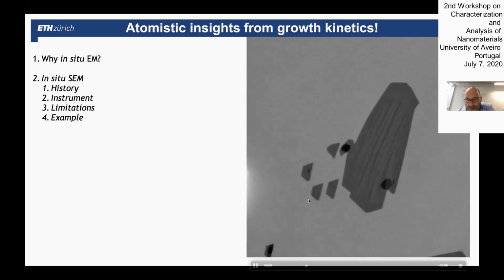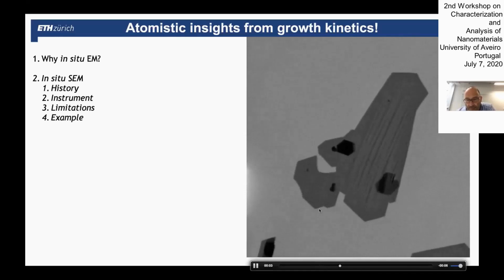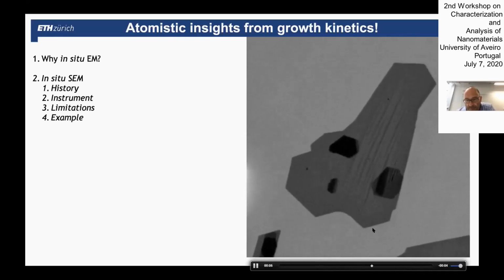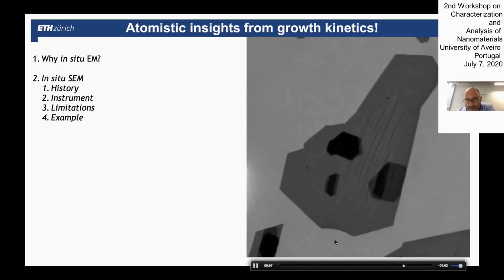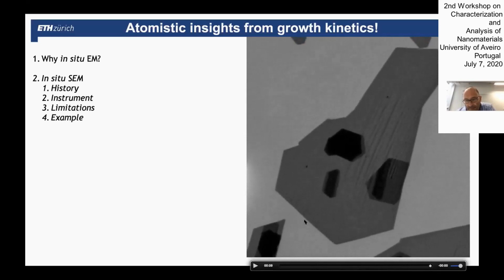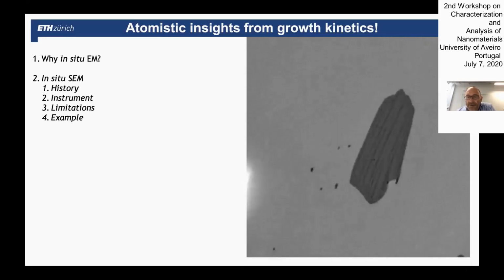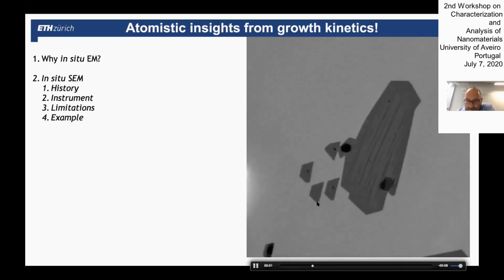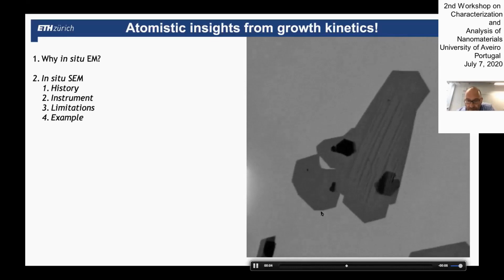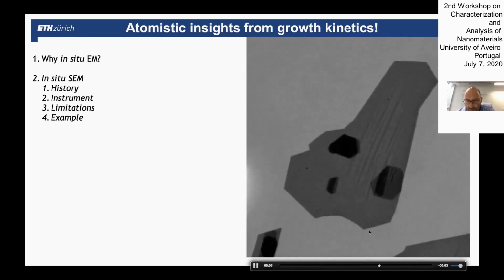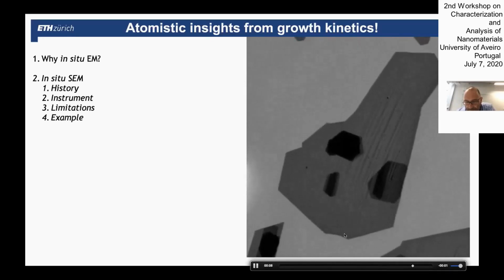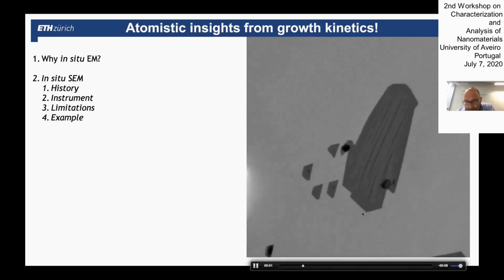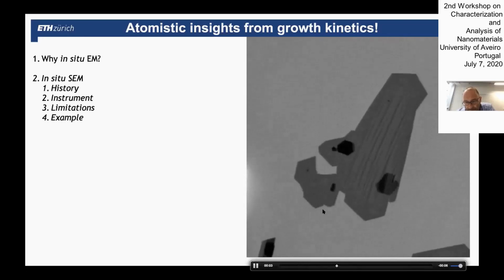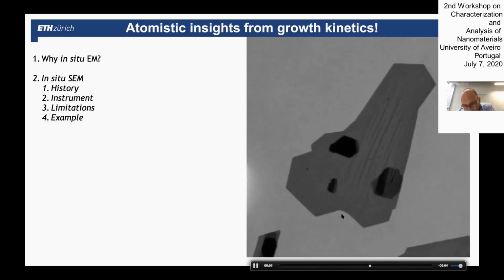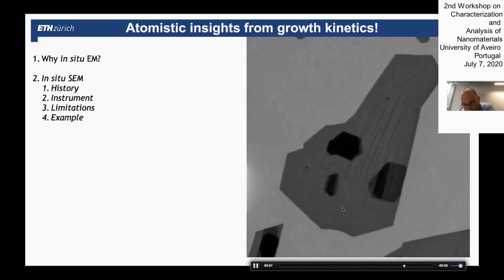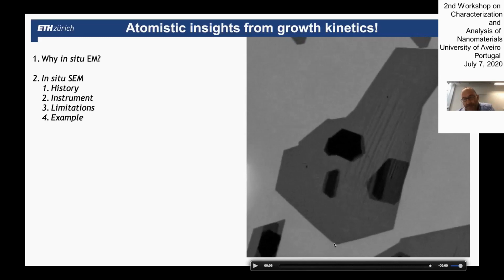You see that these islands grow and there are some points where they meet, the concave angle, but then it grows nicely into a beautiful hexagonal shaped thing. And we studied this growth very precisely, especially how this concave angle turns into convex angle. With this concave angle, it's really lagging behind in the growth, so the concave angle fills up very fast. So it's starting far behind, but it finishes off very fast.